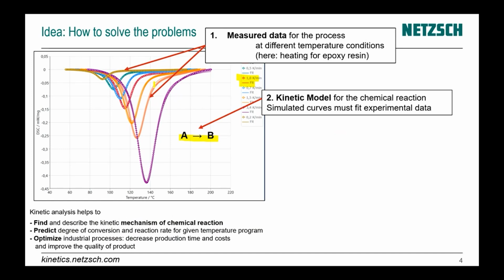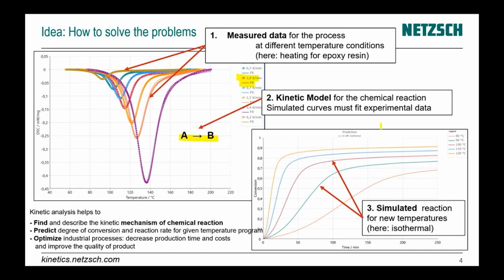After that, we can use this kinetic model to predict the behavior of the chemical system, of the curing system, at another temperature. For example, for isothermal conditions, for 80, 90, here 120 degrees C. And here we can predict, for example, the degree of conversion. We can predict heat flow. We can predict different concentrations, and for multi-step reactions, we can also predict the concentration of intermediate reactants. And this model can also give us the possibility to make optimization of industrial processes.